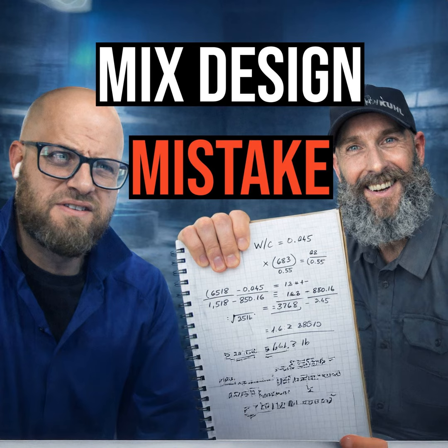Where do you get those numbers from? Is that from the guy that you buy your rock from? Absorption is normally given to you by your aggregate provider, or you can hire a third party who does ASTM C127, and then ASTM C128. There are all these ASTMs you use, but you're basically drawing out the aggregate, saturating it, then drying it, and taking weights in between to give you what that absorption is. And then the moisture content should be listed on the batch ticket.